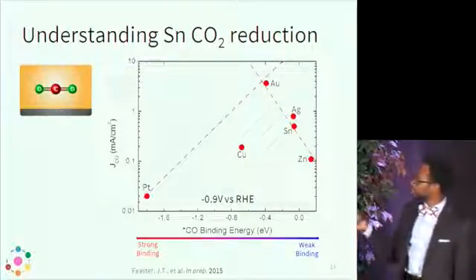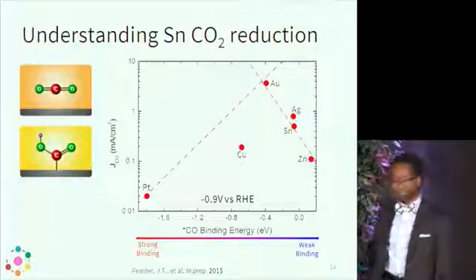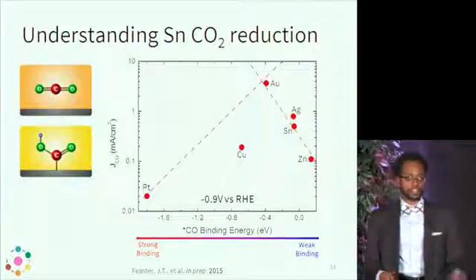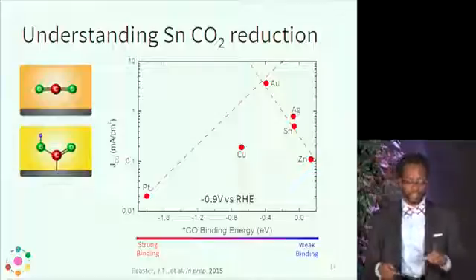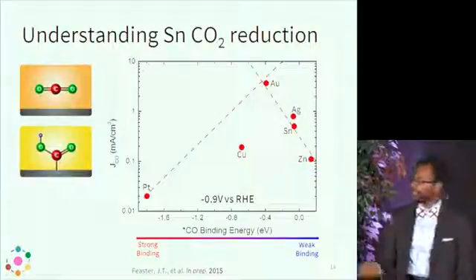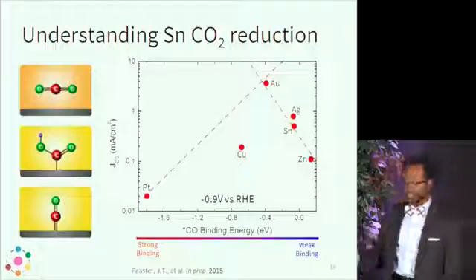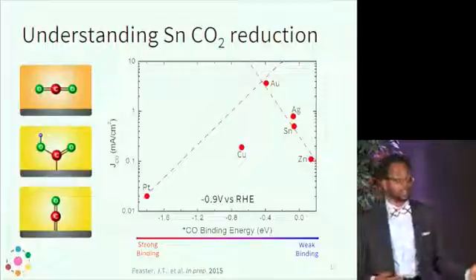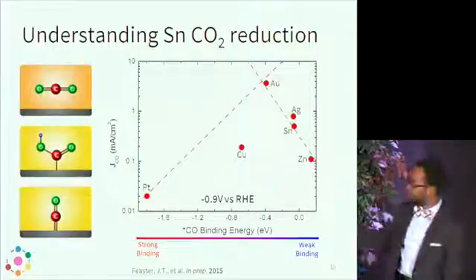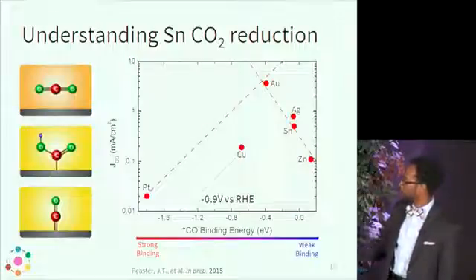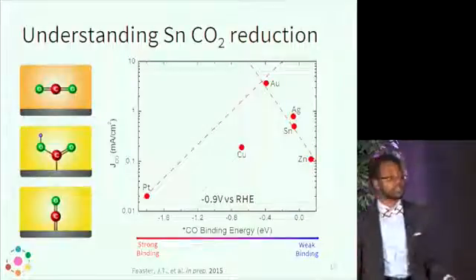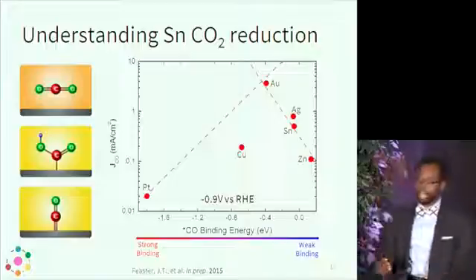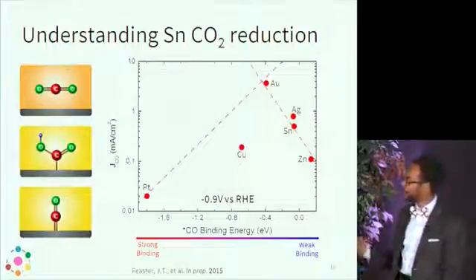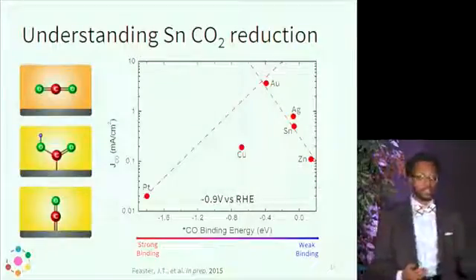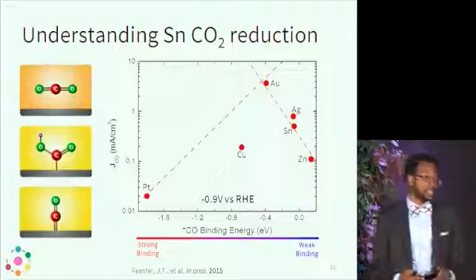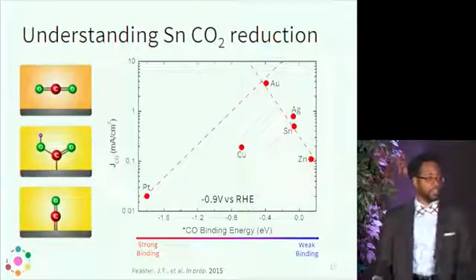reaction. So for CO2, as it's going from this intermediate that we've done the calculations for, its binding energies to the surface, which is a carboxylic acid type intermediate here, as you can see there, and then as that goes to carbon monoxide, it's just one potential pathway for CO2 reduction. You can see that this plot to the right here actually seems like it follows what's known as a volcano trend, which simply means that the binding energy of this key intermediate to the surface cannot be too strong nor too weak. It has to have an intermediate binding energy in order to have an optimal production rate.